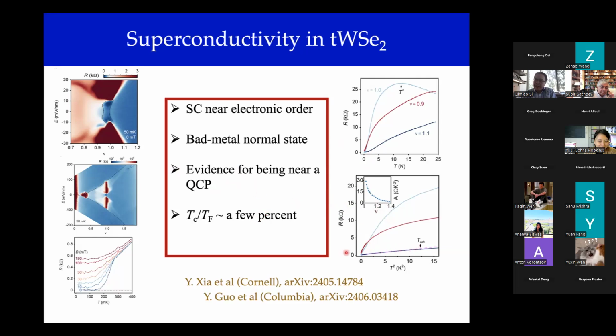This is through a practice that resembles what is done in heavy fermion superconductors. One looks at the Fermi liquid temperature dependence, T-square resistivity, and asks what the slope of this T-square resistivity is, and looks at the A coefficient as a function of tuning parameter. In this case, it's tuning towards the superconducting region from this side.